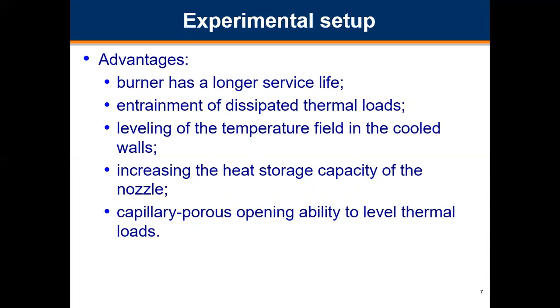The service life of the burner is increased 1.5 times due to the intensification of heat transfer by creating a uniform stable pulsating film on the outer surface of the nozzle, as well as by increasing the dissipated heat load through the high heat storage capacity of the insert with a groove made in it and the capillary porous coating having an anisotropic structure.